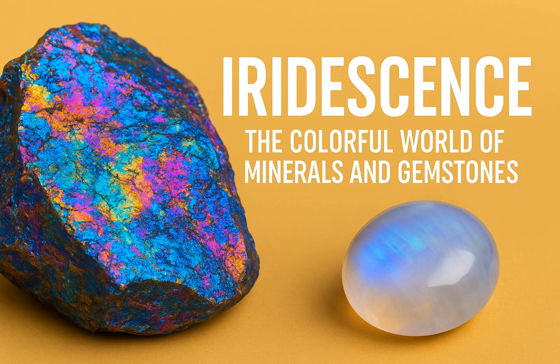Tarnishes, like silver does. Similar idea, but with much more spectacular results. This natural oxidation process creates microscopically thin films of various copper oxides on its surface. And these films then transform into incredible, vibrant, iridescent shades of blue, purple, sometimes even bronze, or a whole kaleidoscope of all three. Wow, so the tarnish is the color. The tarnish creates the thin films that cause the color through interference. It's this dynamic chemical interaction with the air that earns it the nickname Peacock copper or Peacock ore.